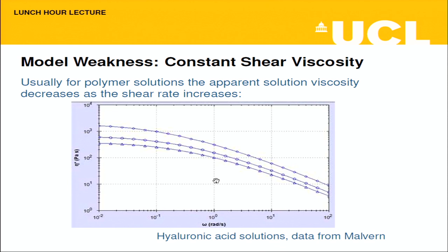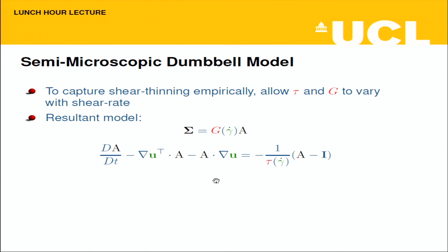The UCM model gets something quite badly wrong: it has a constant shear viscosity. A real polymer solution has a viscosity much lower at high shear rates than at low shear rates — a massive reduction on these log-log plots. So we can empirically modify the model by letting its constants depend on shear rate. I can shove in the experimentally measured viscosity. It's a bit fudgy, but workable. This is called the White-Metzner model.